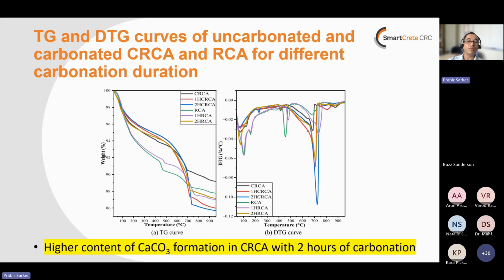So some more evidence of the calcite formation by using the thermogravimetric analysis. For CRCA without any carbonation, CRCA with 1 hour carbonation, 2 hour carbonation, and the other type of recycled aggregate without any carbonation, 1 hour carbonation and 2 hour carbonation. We can see the calcite breaks down in this temperature zone, about 700 degrees centigrade and beyond. So we can see this line, for example, at the bottom is for 2 hour CRCA. So more carbonation of the CRCA had higher calcite content. So higher calcite content means more improvement of the pore structure in the adhered mortar.